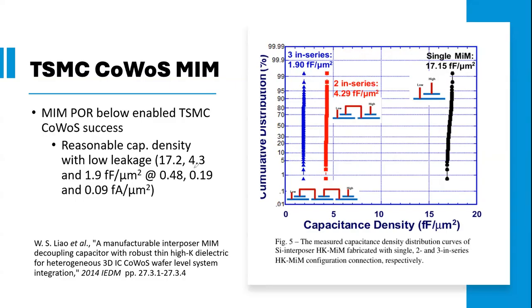And so it has a reasonable cap density, low leakage. See here, low leakage. And the distribution is very sharp. Look at how sharp that is. The slope of this is very steep. So your cumulative distribution curve, when you plot it against some functions, and we talked about this in our last talk about reliability, right? The sharper, the better, and there's no kink inside.